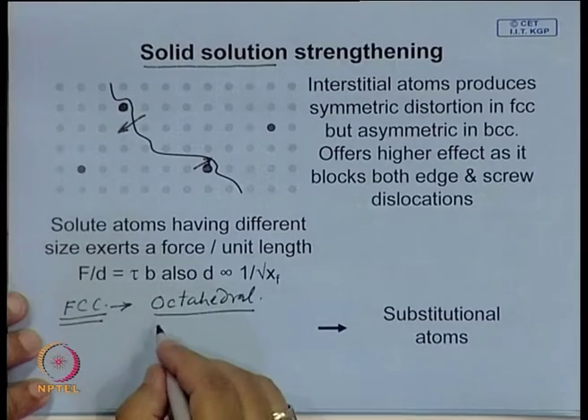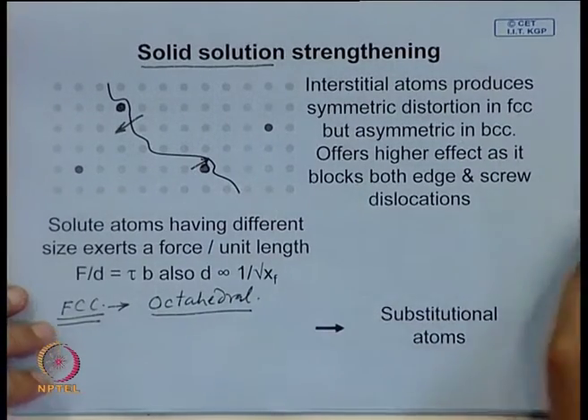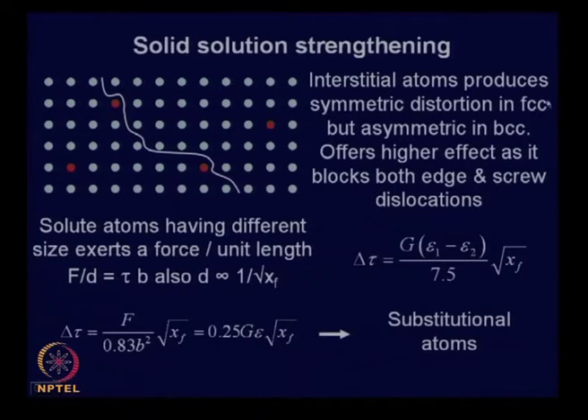and these sites are symmetrical. So, in FCC, whenever you have a carbon atom, distortion that it produces is uniform in all directions, whereas in BCC lattice, even if the carbon atom, whether it is tetrahedral or octahedral, and more likely chance, I mean, people have seen by experiments that carbons prefer octahedral sites, and these octahedral sites in BCC are not symmetric. In one direction it is large and in another direction the interstitial gap is shorter. So, when carbon atom goes into the interstices, it produces expansion in one axis, and that axis is C, and this introduces a tetragonal distortion in the lattice, and this distortion is quite large, and that is a more important factor for strengthening,